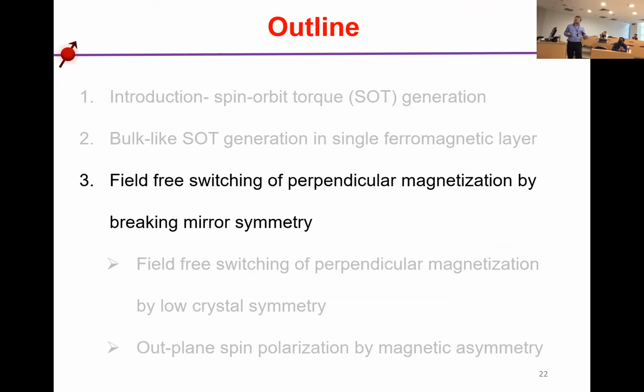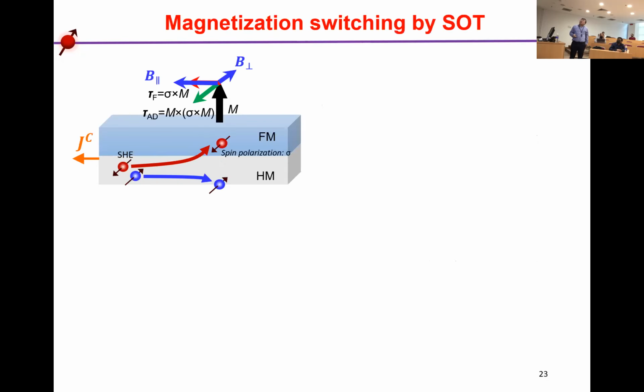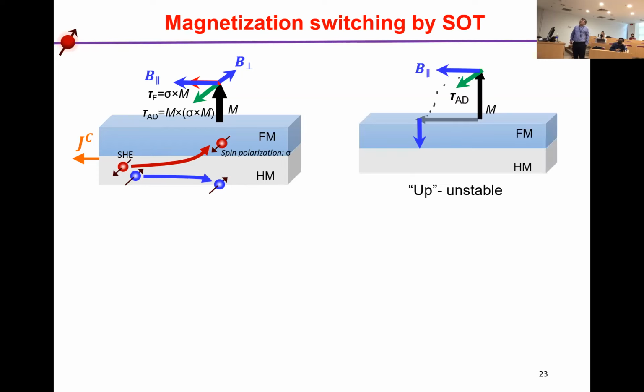And then we discuss field-free switching of perpendicular magnetization by breaking the mirror symmetry. We know that for practical application, we have to use field-free switching. For magnetization switching by SOT through bilayer structures, there is an anti-damping torque and a field-like torque. Only the anti-damping torque plays the main role in switching the magnetization, so here we will not discuss the field-like torque. For the anti-damping torque, there is an effective field along the current direction.